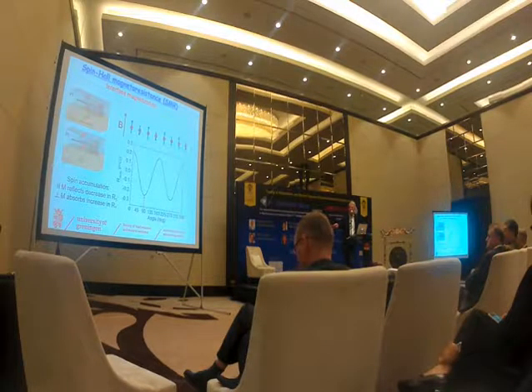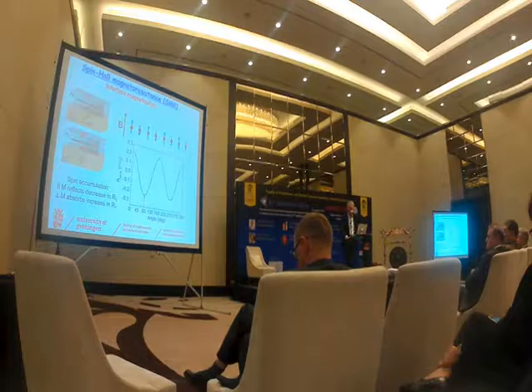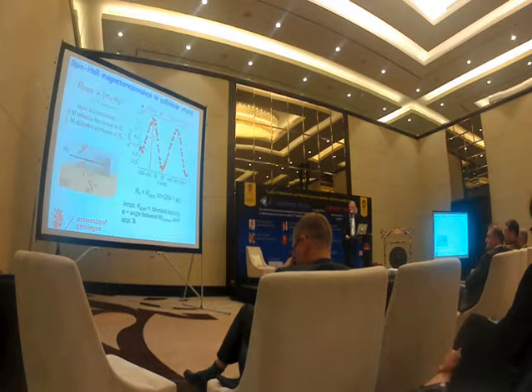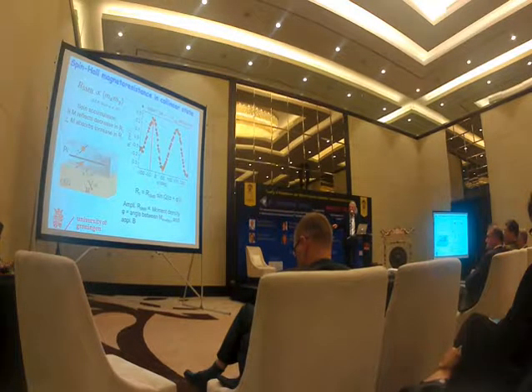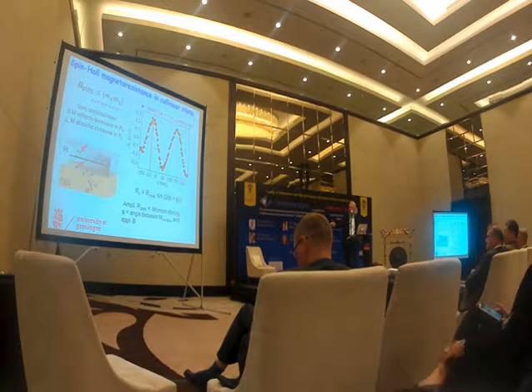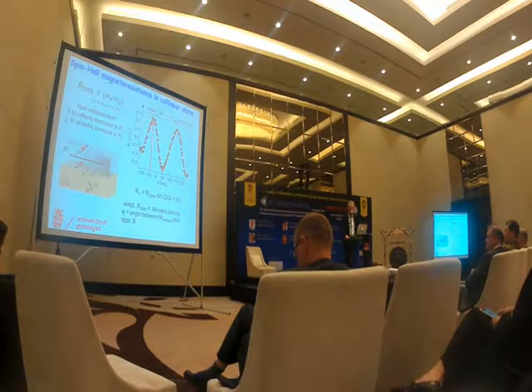You send a charge current through the platinum, and this charge current sends the spin current through your magnetic material, and the spin current is being detected. You can easily measure this by rotating your sample in the magnetic field, where you observe then an angular dependence of your magnetic resistance, and this angular magnetic dependence depends on the symmetry of the magnetic state with respect to the magnetism of the underlying atoms. So these are the measurements where you see the modulation of the magnetic resistance as a measure of the spin currents injected in your magnetic material.